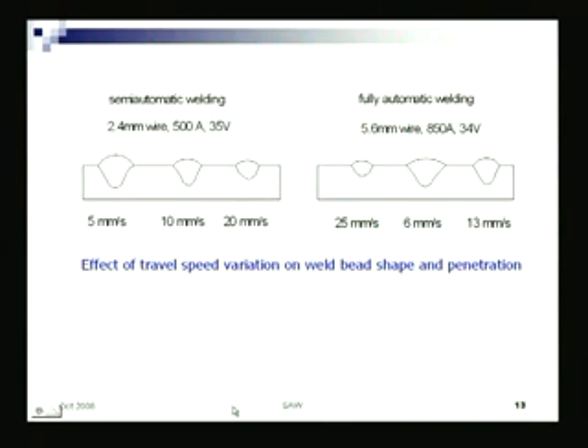This is shown schematically: here at 25 millimeters per second versus, for the same parameters, look at the depth - here it was 13, now it is 6, as if the speed is halved. So what has happened? It has become wider, but depth has not increased.